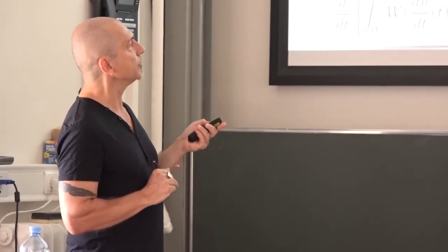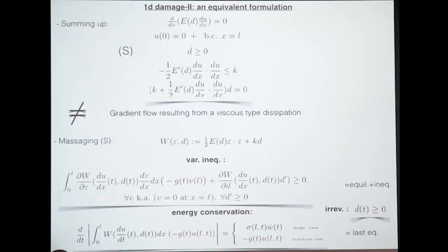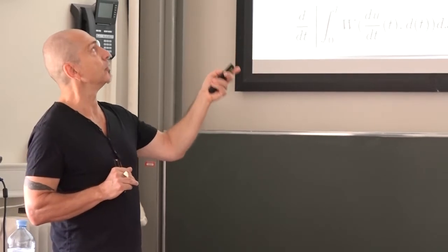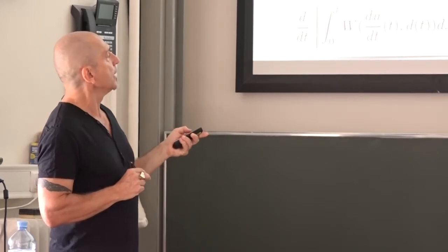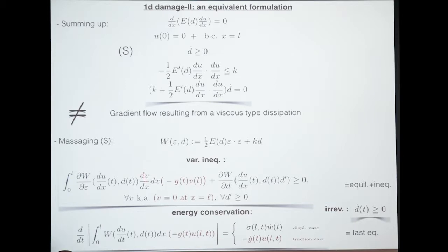So let's take a little bit of time. So W is a function of epsilon and D. I replace epsilon by du dx, D is D, and then I do variations both in V and in D, which is why you have a dW over d epsilon here, a dW over dD here, and then this term here is in red because it only comes into play if you're doing a traction at the right-hand side of the bar. And now, what are the V's that you can take as test functions? Well, those are kinematically admissible V's. So that's a word to say that in the case where you have a force, V is not constrained. In the case where you have a displacement at that end, then V should be 0 at that end. And as far as D prime is the test in damage, the damage test functions, if you want.